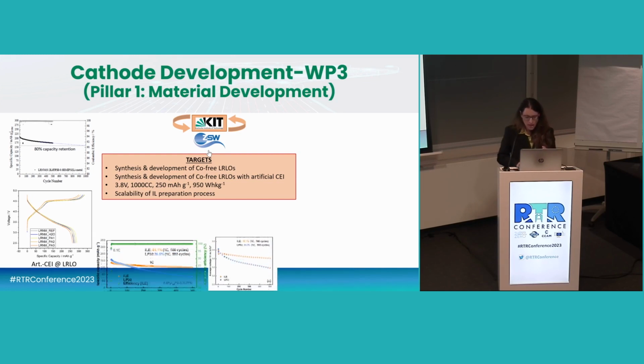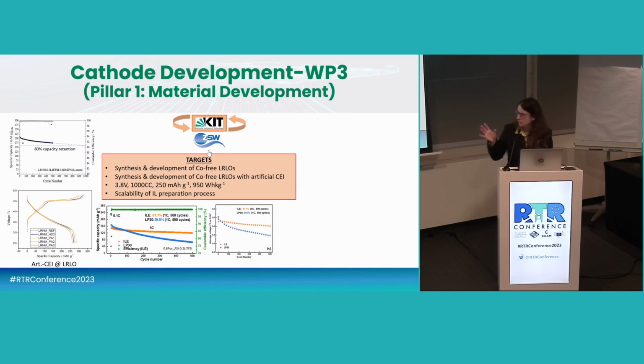This was the strategy. And what was really impressive for us was to see how we achieve this kind of stability, and you can see the orange graph, within 500 cycles, exactly using the ionic liquid formulation that was the successful one that the work package 2 developed. So the work package 2 found which was the optimal composition of this ionic liquid. And what was really surprising for us was to see how well this composition was working. I didn't show the performance of the anode cell, but for both the anode and the cathode, we were having very good performances with this kind of formulation that was identified within the work package 2. And again, here we are showing that we are having a cell stability within the first 500 cycles.